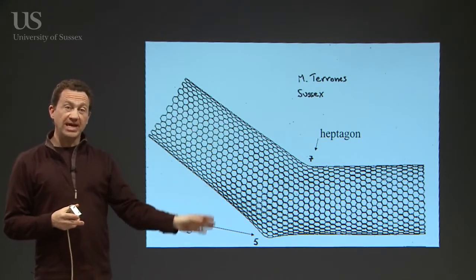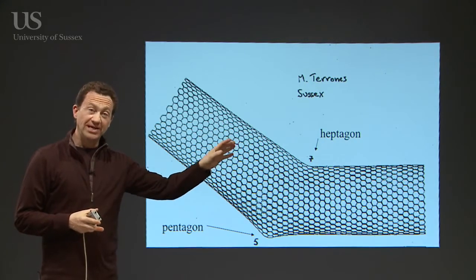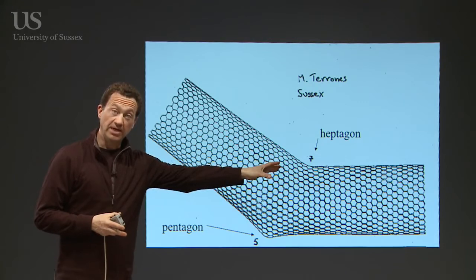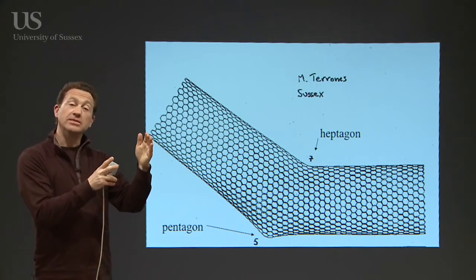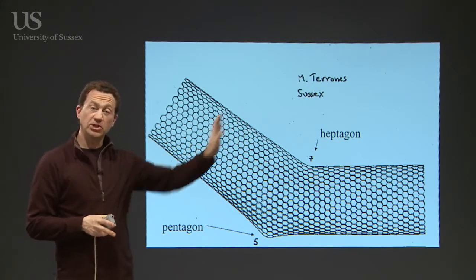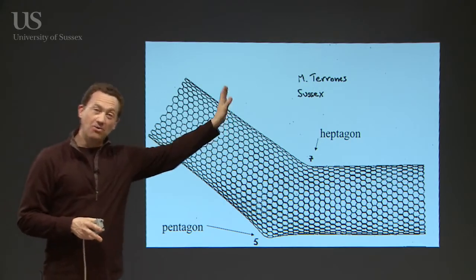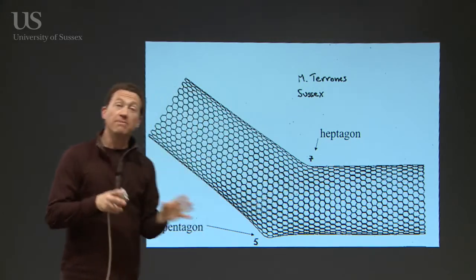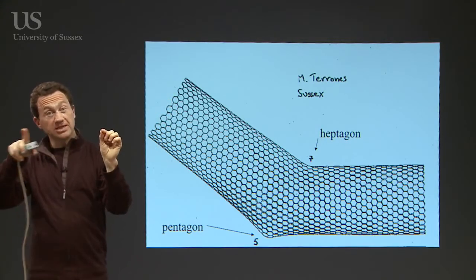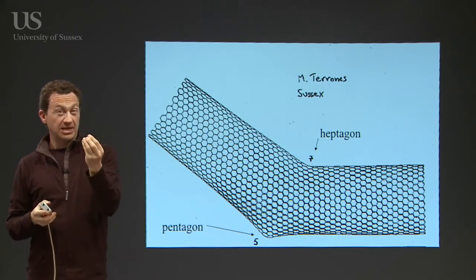This is a straight nanotube where one of the hexagons at the bottom has been made into a pentagon, and one of the hexagons over here has been made into a heptagon — a seven-membered ring. If you do that, it bends the tube, and it turns out that affects electrical conductivity as well. So one part of the tube might be conducting and another part insulating, allowing you to make a little electronic component — conducting, insulating in the middle, conducting again — perhaps a diode or a tuning capacitor, all on the nanoscale.